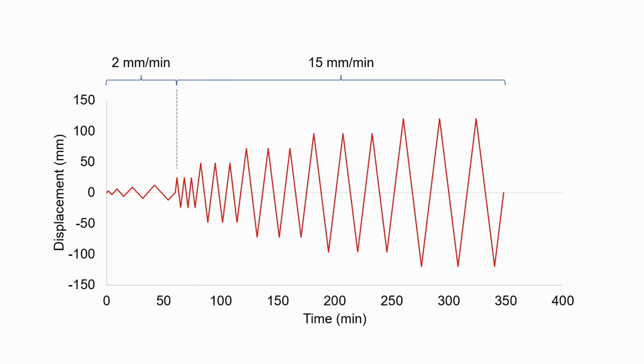And this is the displacement sequence. Initially, before yield, we applied 1 incremental displacement up to about a displacement level of 12 millimeters, and then we applied 3 repetitive displacements that increased up to about a drift ratio of 10%, or 120 millimeter displacement on each side.